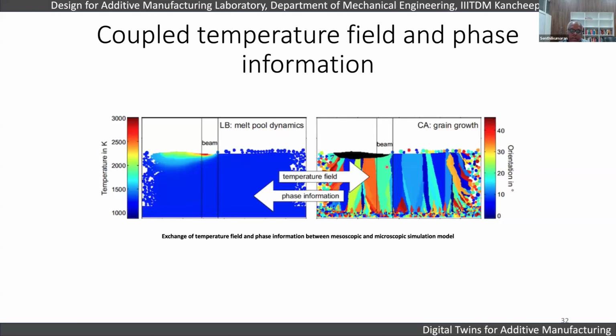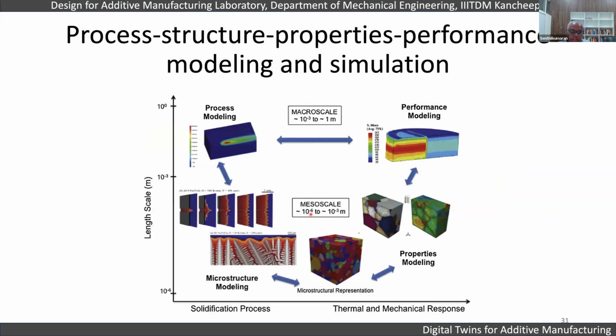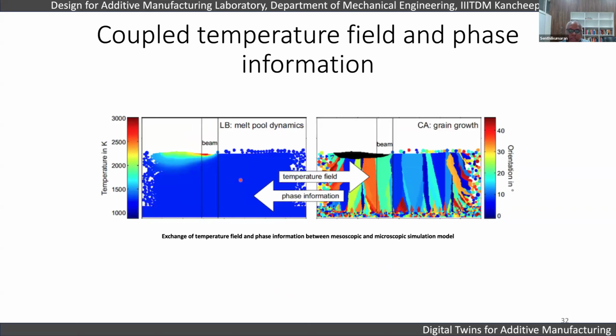So you get the temperature field, right? And then you get a microscopic simulation model. Here you're trying to basically simulate the grain growth, and then use that phase information again here to create that solidus liquidus information here. So you can use it as a coupled method. So here you can use both the phase information and the temperature information. That's why you can see some of these arrows are bidirectional, meaning when you're simulating, the information is being passed back and forth, right? So that is how the temperature and phase information is being used in the coupled model.